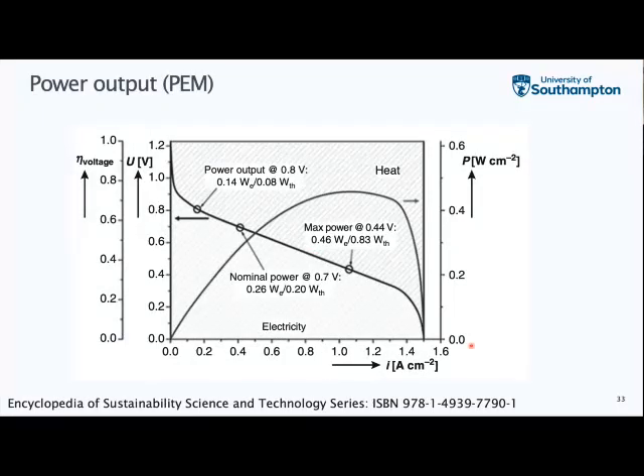What that means in terms of power output is a peak power generated from the cell voltage. So if you plot the cell voltage against the current or the current density per unit area, you have the polarization curve that we saw previously. But then when you multiply up the voltage by the current to get the power, you get a peak power region for the fuel cell, and particularly with fuel cells you want to be operating at the most efficient point. Hence where you can bring in some hybridization, so you're always running the fuel cell at an optimum efficiency or power output, and either supplying a load or charging a storage battery with excess power.